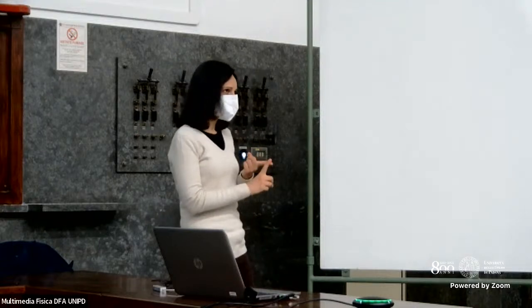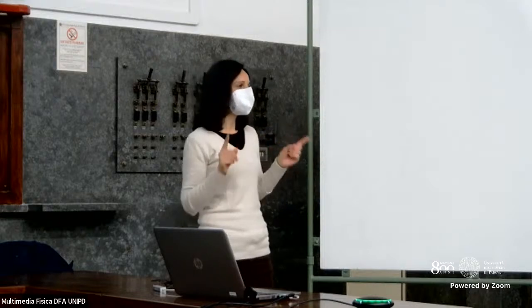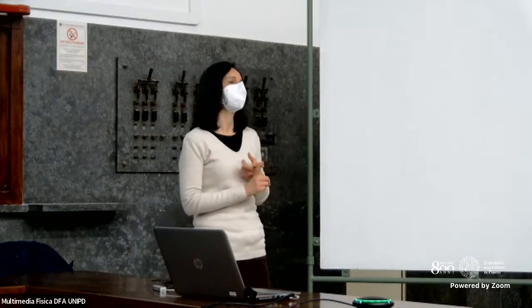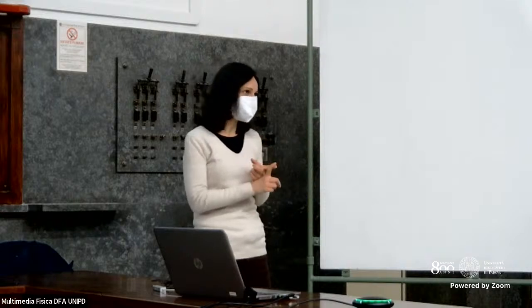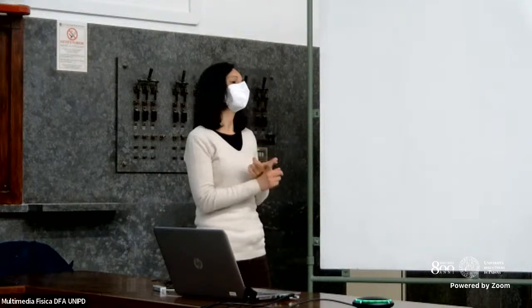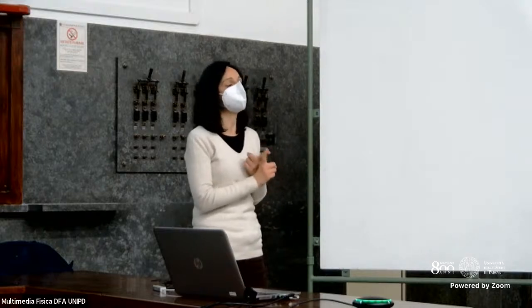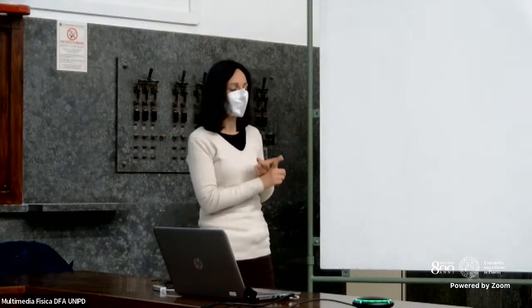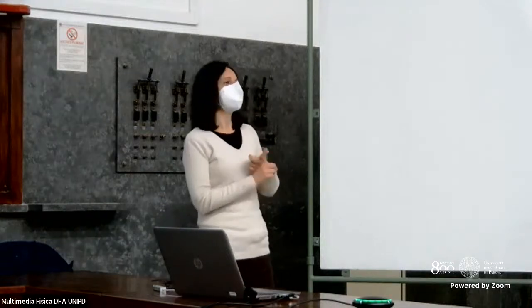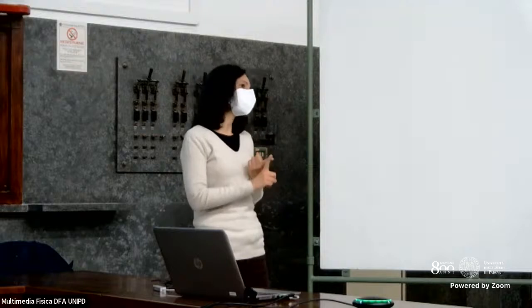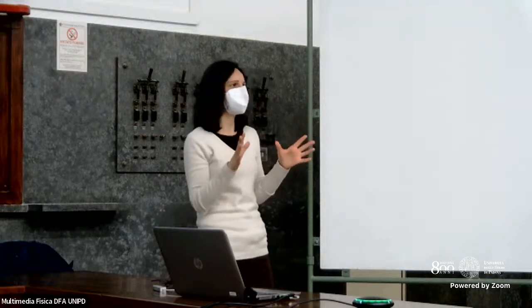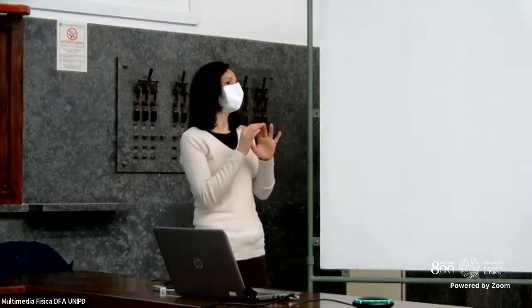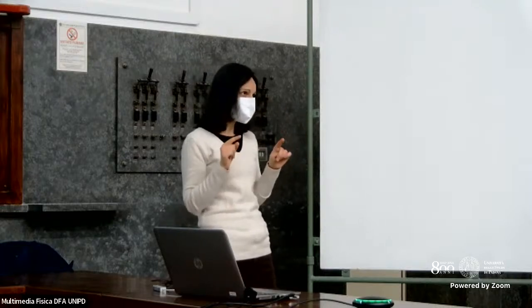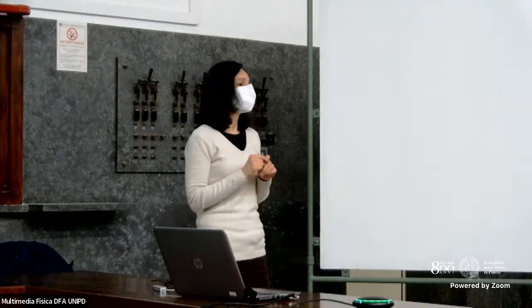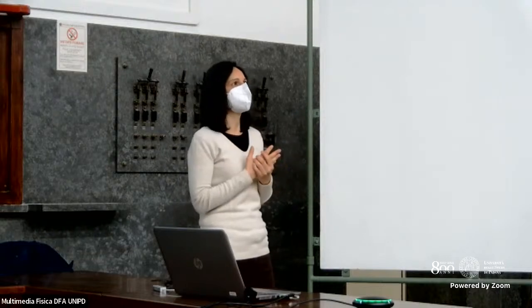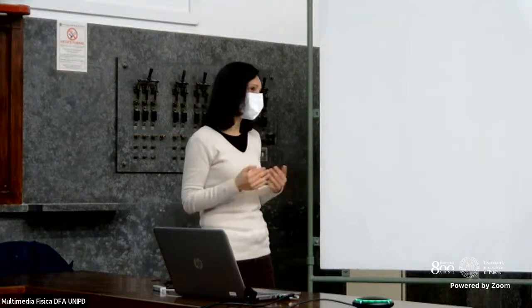Very interesting. About numbers for electrospinning, with laboratory scale equipment one can produce grams of fibers per day. The typical flow rate is a few milliliters per hour of a solution. Depending on the polymer and the solvent you use, in 1 hour you can cover, at laboratory scale of course, an area of 10 by 10 centimeters squared, with web thicknesses from tens to hundreds of micrometers.